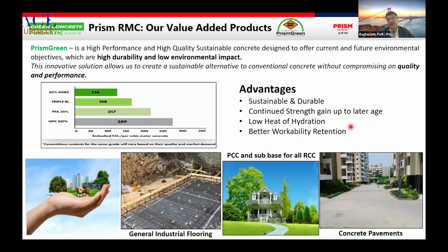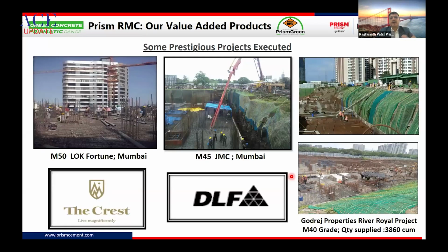Low heat of hydration, because we reduce the cement content, hence the low heat of hydration. It helps to reduce thermal cracking in concrete, and it gives better workability retention. Nowadays, in most of the major cities, the foundations or rafts are coming in a very big size, like 2.5 meters, 3 meters, and in mass concrete the heat of hydration is very high. As per the new code, the core temperature is very important. The core temperature should not be more than 70 degrees, and the temperature gradient, the differential temperature between core and surface, should not be more than 20 degrees, to avoid thermal cracking in concrete.